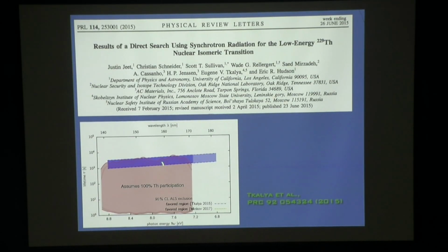We couldn't go here because the ALS, they just weren't allowed to tune it there anymore. And we couldn't go up because we just needed more flux. The ALS makes a lot of photons, but its line width is quite broad. When you're driving a transition that's like a millihertz wide, right? In the crystal, it's broader than that, but still, it's a very narrow transition with a broad source.